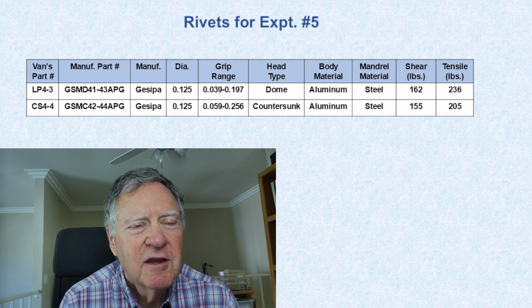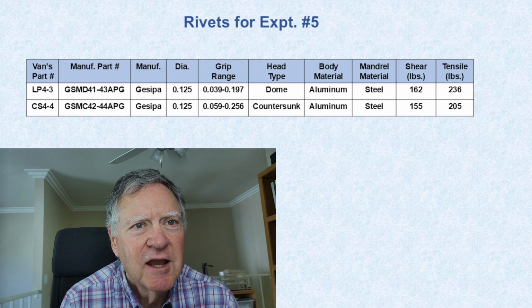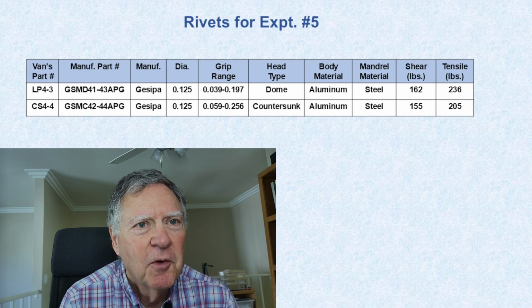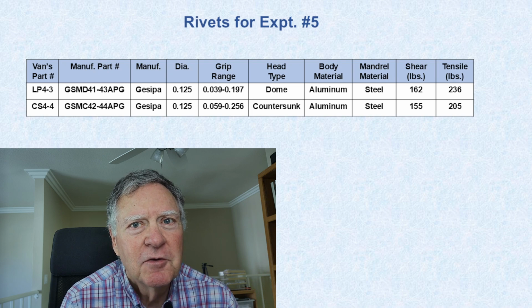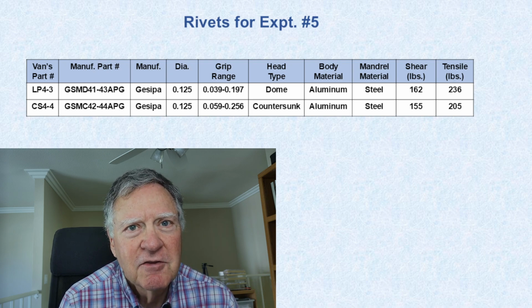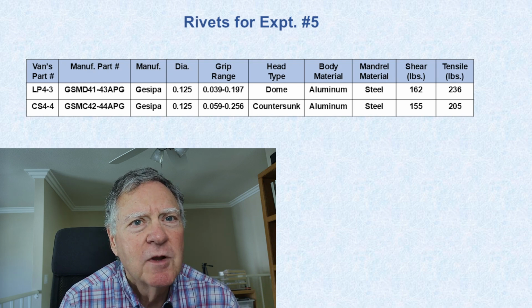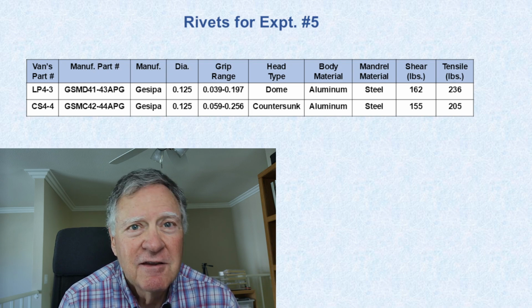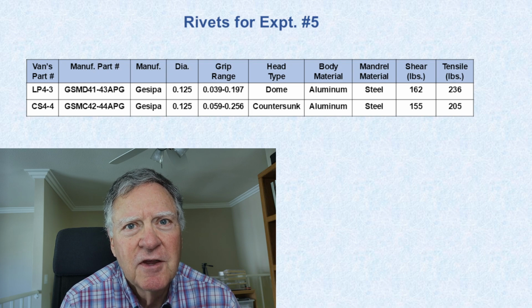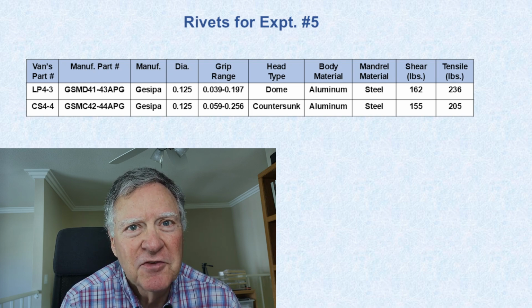That's where the 41-43 comes from. The 4 means that it has a diameter of 4/32 or 1/8 of an inch. The 1 in the 41 means that it has a maximum grip of 1/16 of an inch, and the 3 means that it has a maximum grip of 3/16 of an inch. So since this is a 41-43, it means that it has a grip basically from 0 to 3/16 of an inch. And the grip range is shown in the table, in column number 5. And it's from 39 thousandths to 197 thousandths. 39 thousandths is pretty small. 2 16 thousandths skins would be 32 thousandths, and that's about as thin as you can go.